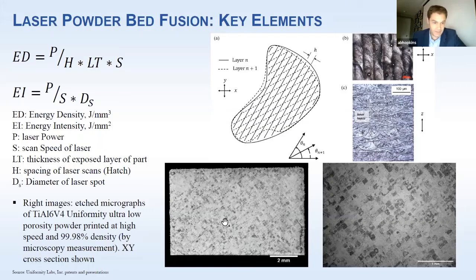But you can get to 99, 98% density on some materials. Aluminum, silicon, magnesium, probably not. I'll get to that in a second. But on some like titanium and on 316L, you can do this, and you can do it quickly. You can see the edges are a little bit different than the middle. Sorry, I don't have a more zoomed in image.